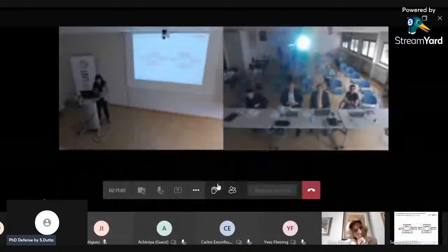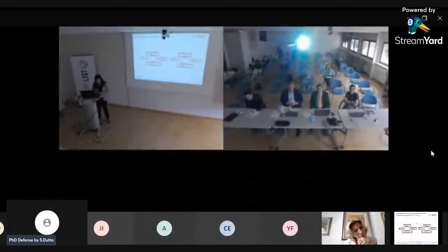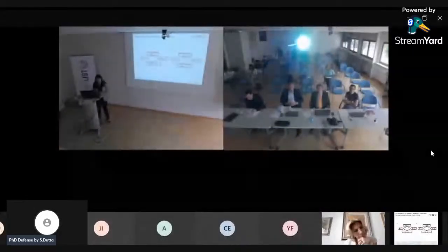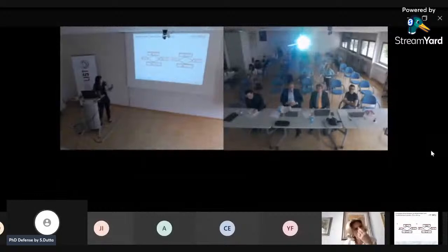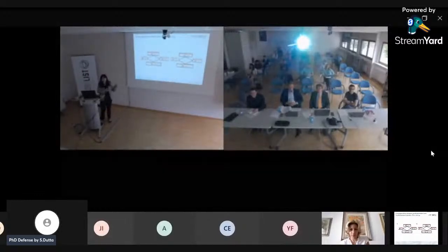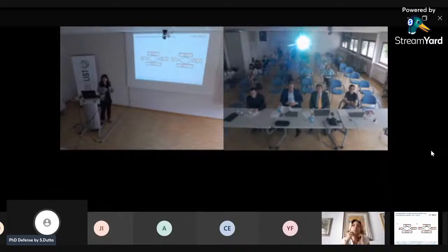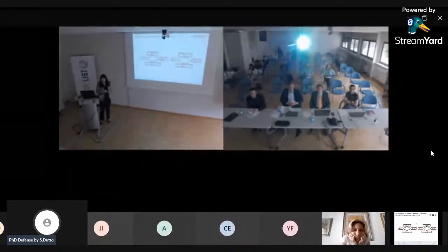Yes, and we also wanted to understand the piezoelectric response of the dopants. That's what we have done. We wanted to understand whether it is coming from the strain it is creating in the lattice or it is due to its local environment. And in that study, what we understood is that the local dopant response is the dominant factor.